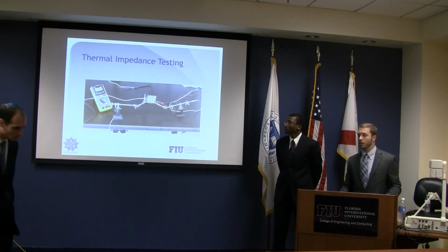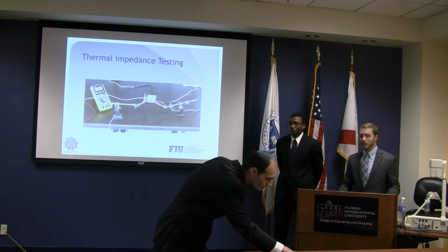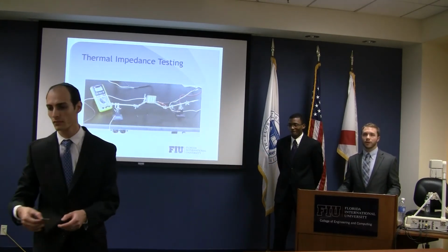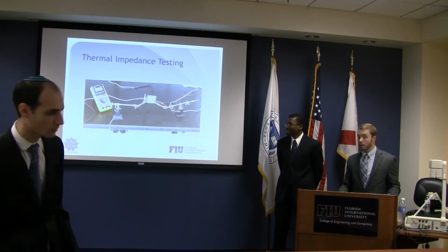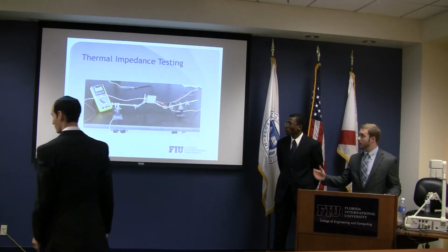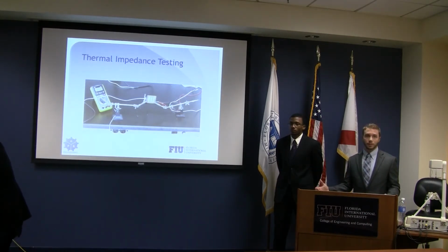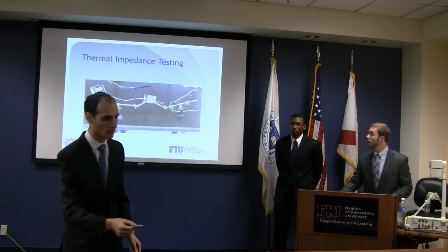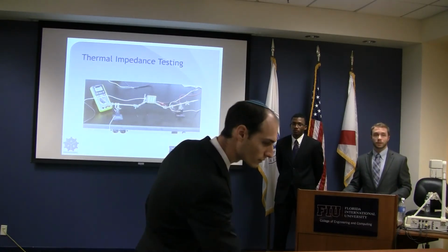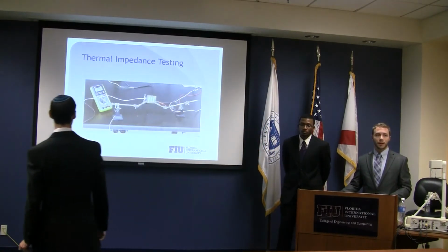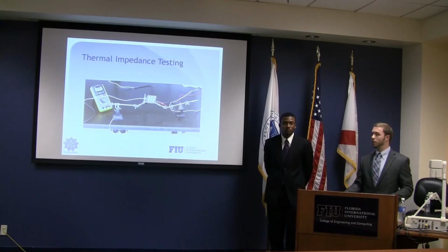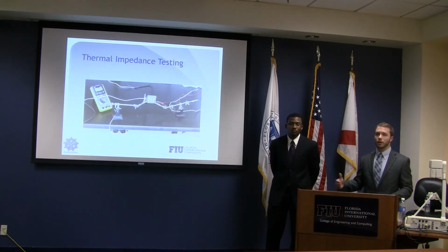This is the MIL Standard 883. Essentially what you see here is a K-type thermocouple embedded in an interface between the resistive heater, which is on the back side, which is connected to a power source supplying the power to heat the actual element. In the interface, we had a silver compound that was a thermal grease that allowed for decent conduction between the resistive heater and the board.